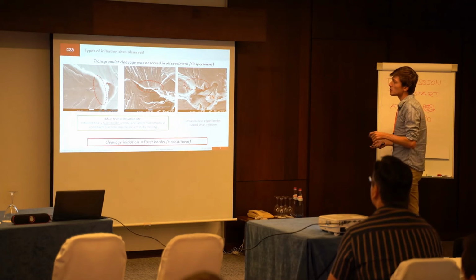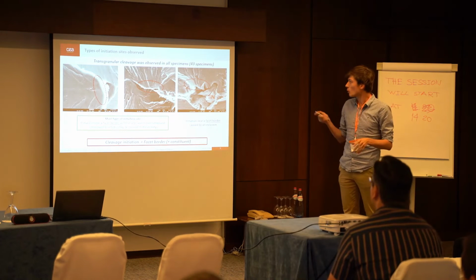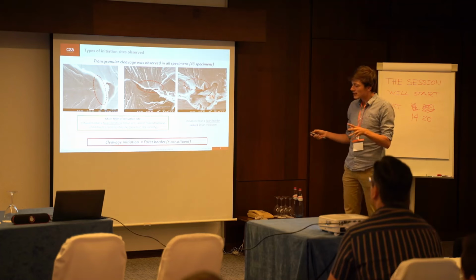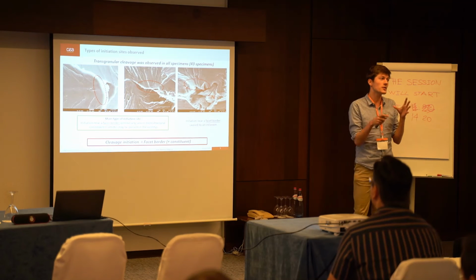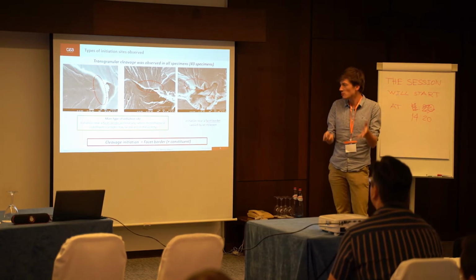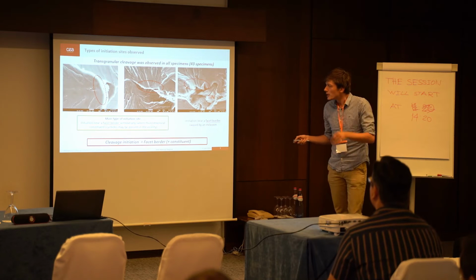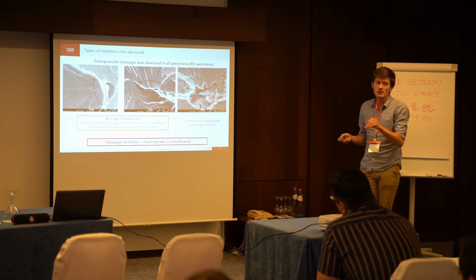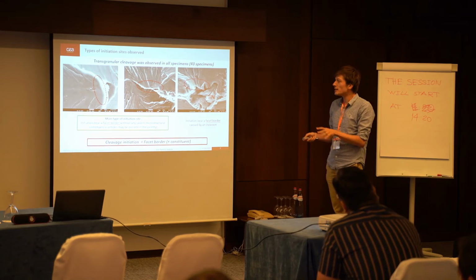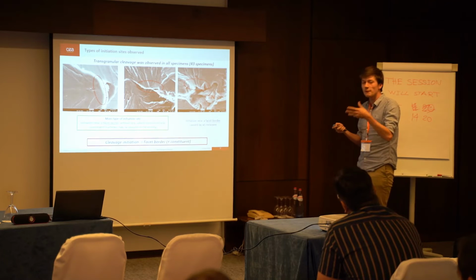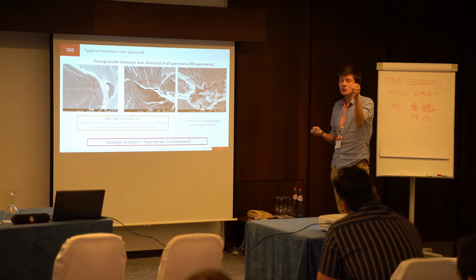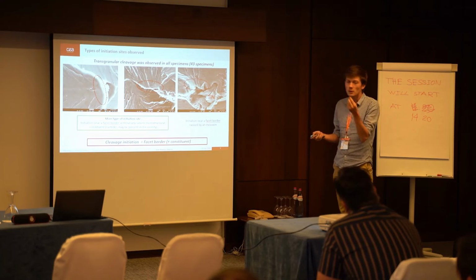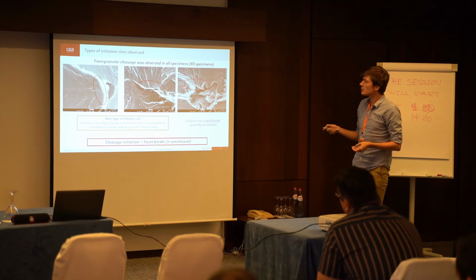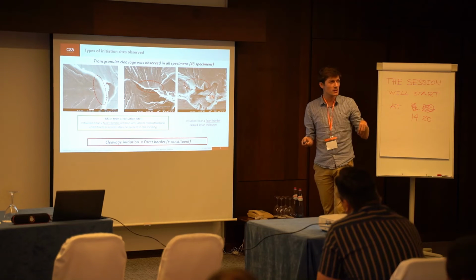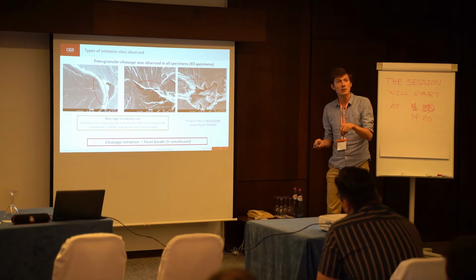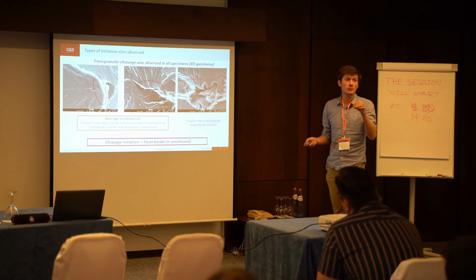Now if we look at the results, transgranular cleavage was observed in all specimens, all 43 specimens observed. What is interesting is that all the specimens, whatever the materials, share the same brittle fracture initiation mechanism. If you look at the picture on the left, you see a facet border here, and there is no microstructural constituent that is visible. This is the most common case. Thus, the brittle fracture initiates at what is likely to be a microstructural boundary, but there is nothing that could have caused the rupture. We also have a case where you can see traces of carbides in the very vicinity, but you cannot link the initiation with the carbides. But it always happens at the facet border.